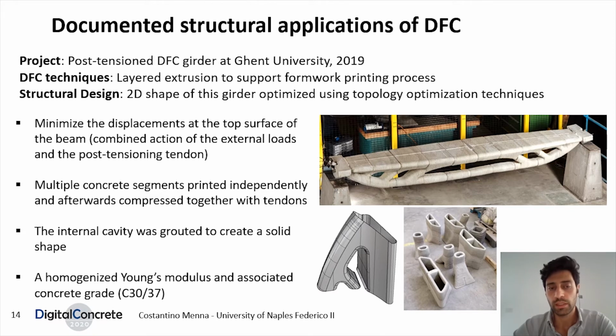The first one is that the 2D shape of this girder was optimized using a topology optimization technique. And secondly, the layered extrusion technique was actually used to support a formwork printing process. In particular, the topology optimization aimed to minimize the displacement at the top surface of the beam and also against the post-tensioning tendons. Moreover, the internal cavities of the optimized concrete segments were filled to create a solid shape. The result is that each concrete segment is a full solid, and in terms of calculation input, a homogenized Young's modulus was associated to the combination of layered extruded concrete and poured concrete.